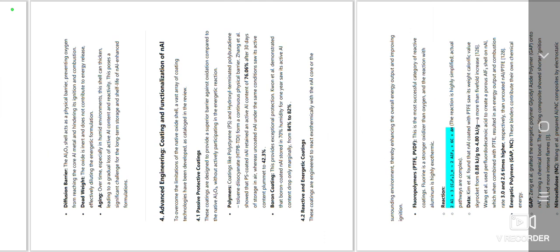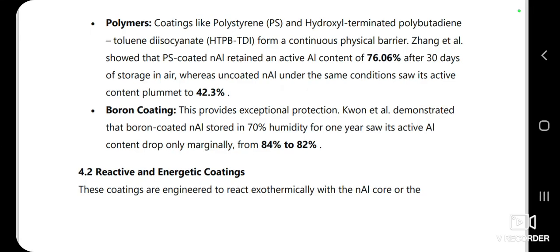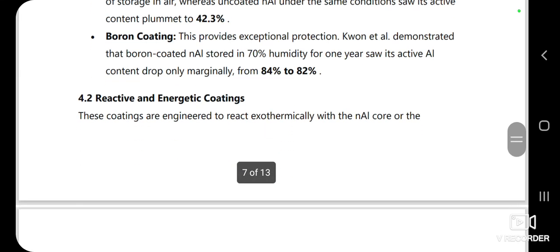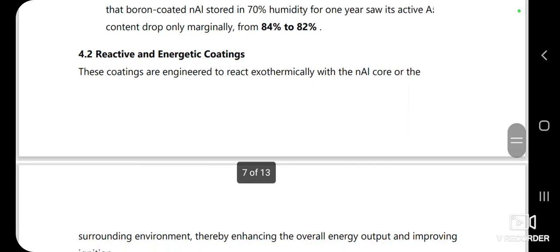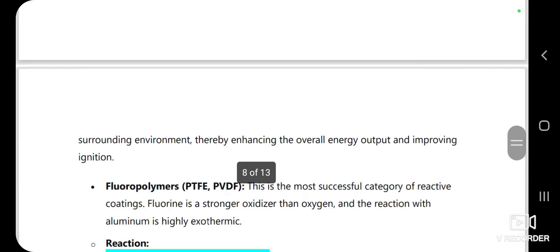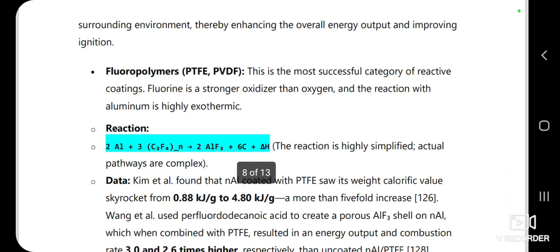And the other is boron coating. This provides exceptional protection, and it's demonstrated that boron coated nano aluminium stored in 70% humidity for 1 year saw its active aluminium content drop only marginally from 84% to 82%. Next we study reactive and energetic coatings. These coatings are engineered to react exothermally with the nano aluminium core or the surrounding environment, thereby enhancing the overall energy output and improving its ignition.